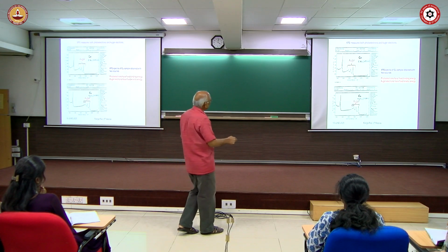This is the spectrum which I recorded. I showed some earlier electron spectrometers, and one of those old spectrometers was used to record this. Here, this is a copper sample, with magnesium K alpha and aluminum K alpha, and I used both. The Auger peaks come at the same value, around 800. So it doesn't depend on whether you use magnesium K alpha or aluminum K alpha.